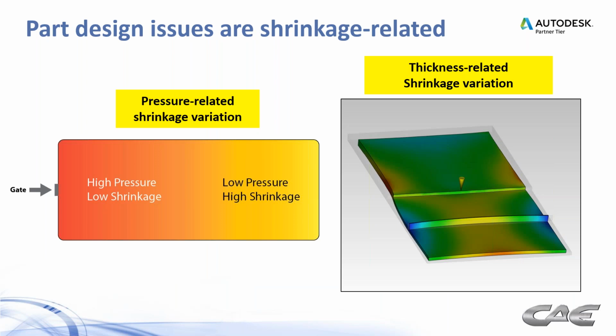Part design issues. In previous webinars, I've shown that part design or warpage is a very shrinkage related issue, and it's shrinkage related in 2 ways. Number one, we've got pressure issues with the gating, right? So areas with high pressure tend to see low shrinkage, and areas with low pressure tend to see high shrinkage. So our gating scheme matters in terms of how the shrinkage plays out. But not only that, we've got thickness related shrinkage variation as well.